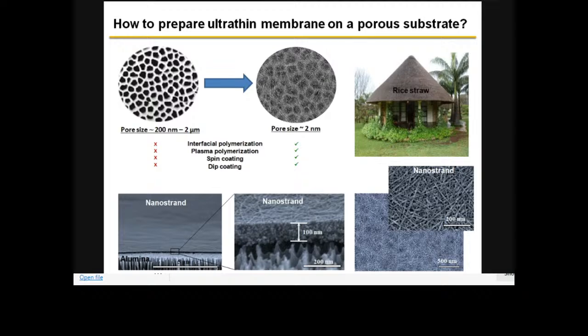To do that, we introduce a nanostrand layer, something like rice straw in a village hut, so it can actually cover the big pores. And on top of that nanostrand layer, we can make our thin film. In the lower SEM image you can see we have made a very thin nanostrand layer on the alumina support. The pores of the support are clearly visible, and on top of that we can cover the pores with the nanostrand layer.